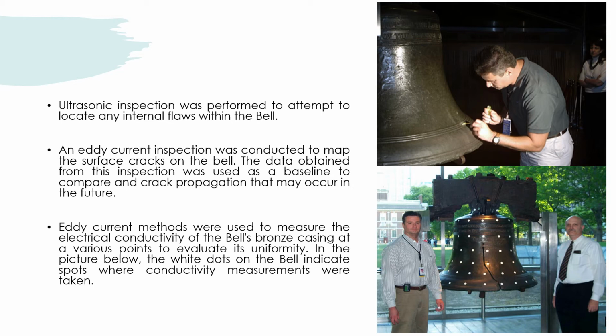The eddy current method was used to measure the electrical conductivity of the bell's bronze casting at various points to evaluate its uniformity.